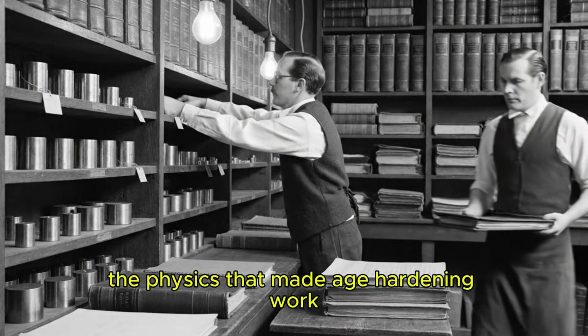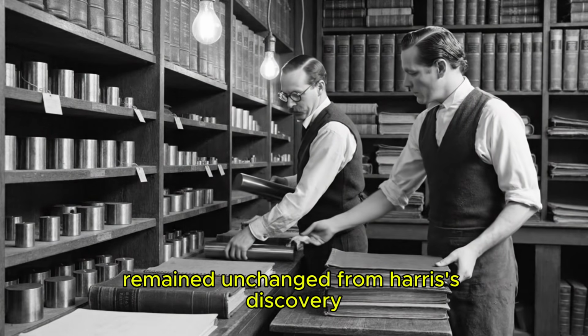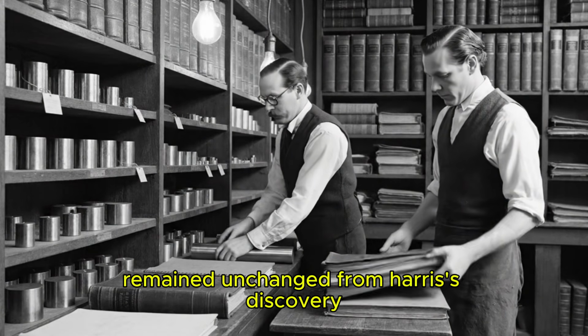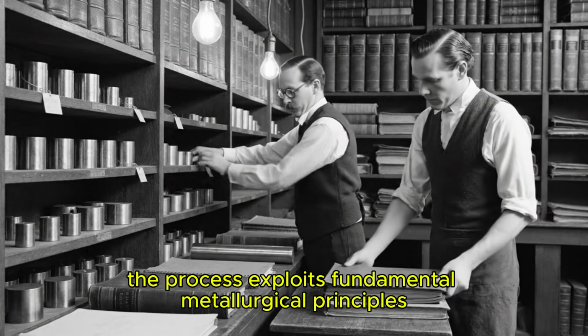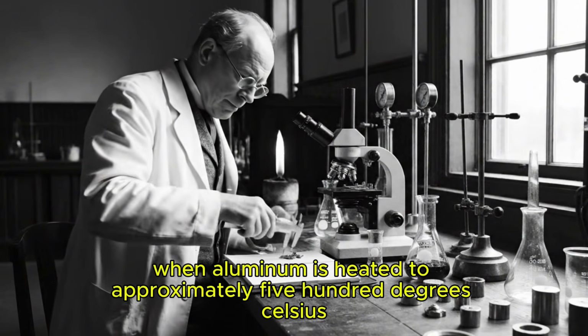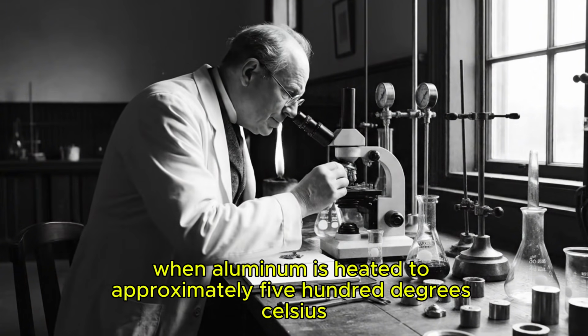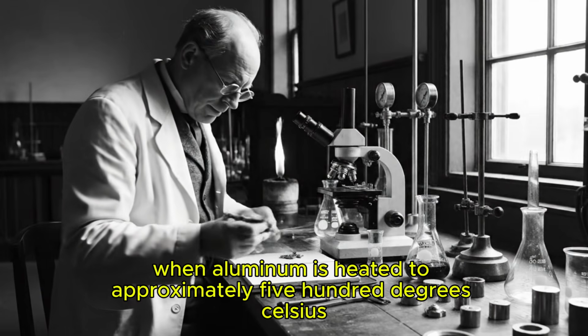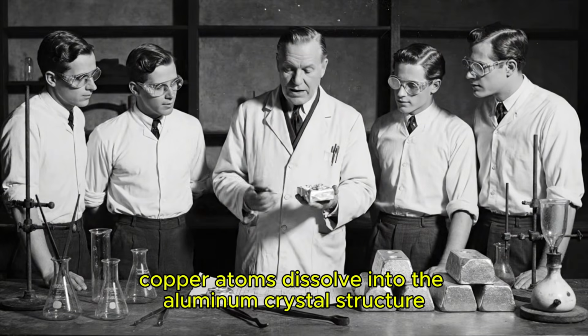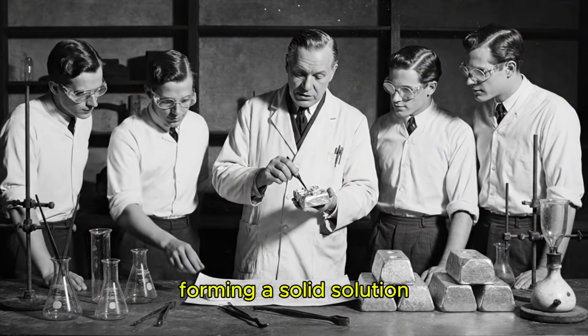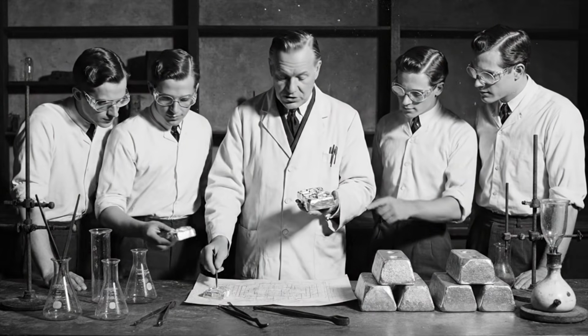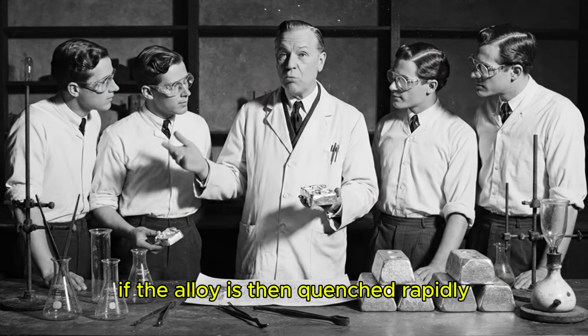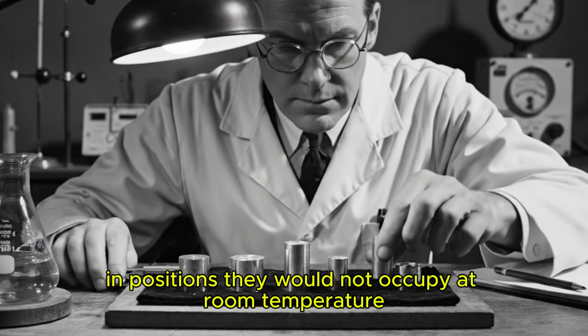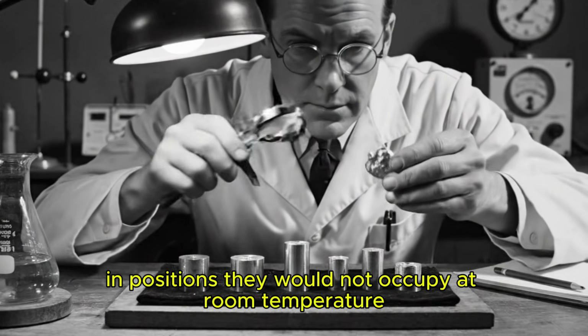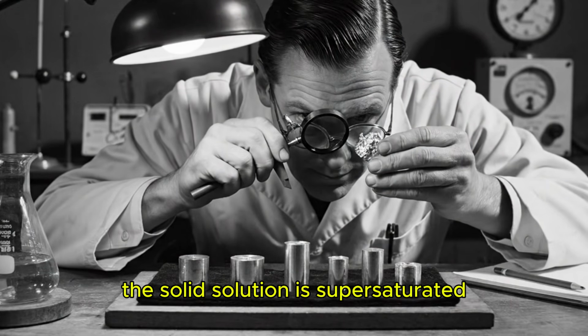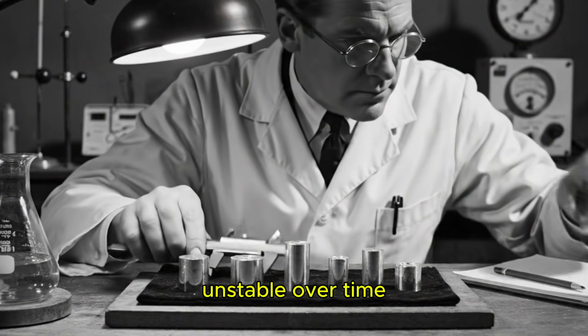The physics that made age-hardening work remained unchanged from Wilm's discovery. The process exploits fundamental metallurgical principles. When aluminum is heated to approximately 500 degrees Celsius, copper atoms dissolve into the aluminum crystal structure, forming a solid solution. If the alloy is then quenched rapidly, copper atoms remain trapped in positions they would not occupy at room temperature. The solid solution is supersaturated, unstable.